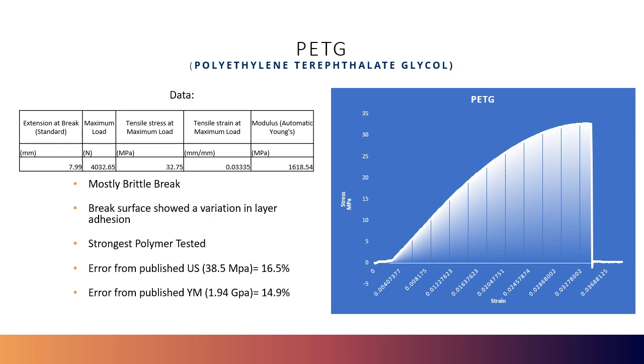break surface showed some severe delamination between, I'd say, 50% of the layer lines, and so I think that's accounting for a lot of this error.